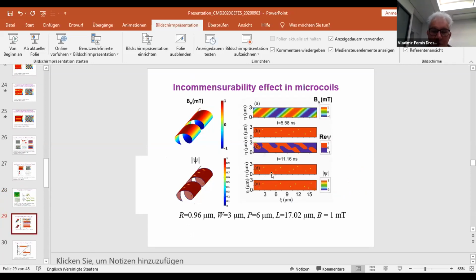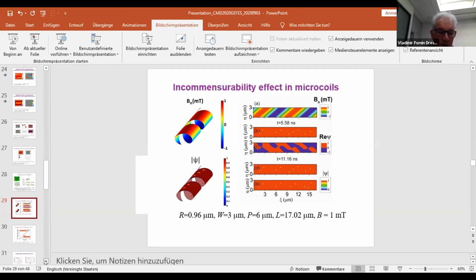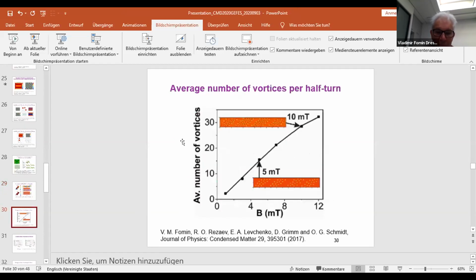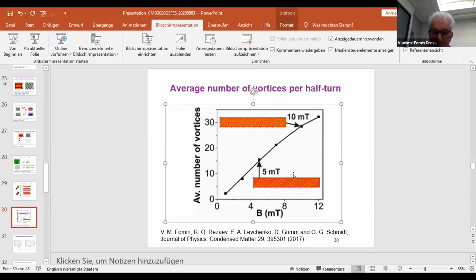Depending on the magnetic field, we can arrive at incommensurability if there should be such a number of vortices which cannot be divided by the number of half turns, then these vortices may occur in different places. The geometry of the nanohelix significantly influences the pattern of vortices. Here we have in every half turn maybe 4 vortex stripes, and here 6.